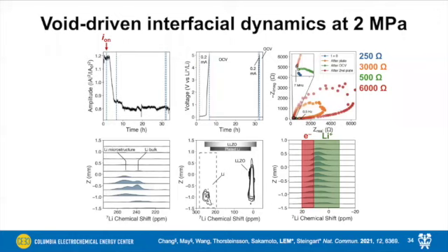The only reason we get good resolution is likely because these phases have unpaired electrons in them. They're good electron conductors. They're shifting to higher frequency. The higher frequencies that we have over here are in the direction of lithium metal. So we know lithium metal is a great electron conductor simply due to the fact that it's a metal. And this is consistent with a lot of the intercalation compounds that form in other battery materials.